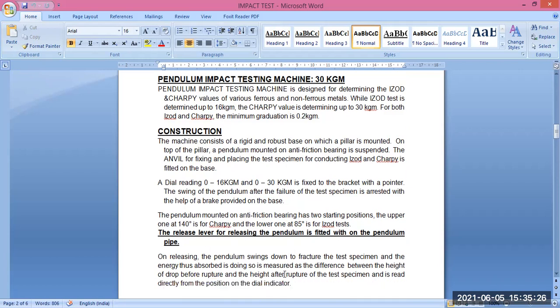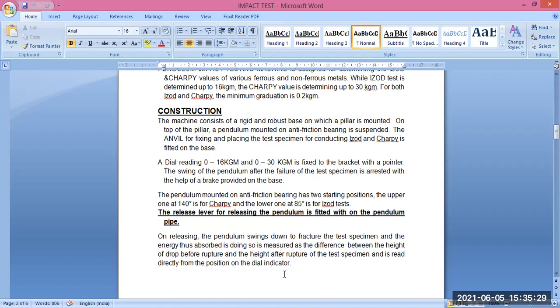Then release the lever of the pendulum. On releasing, the blade of the pendulum fractures the test specimen, and the energy thus absorbed in doing so is determined from the difference between the height of drop before the rupture and the height after the rupture of the specimen, read directly from the position of the dial indicator itself.